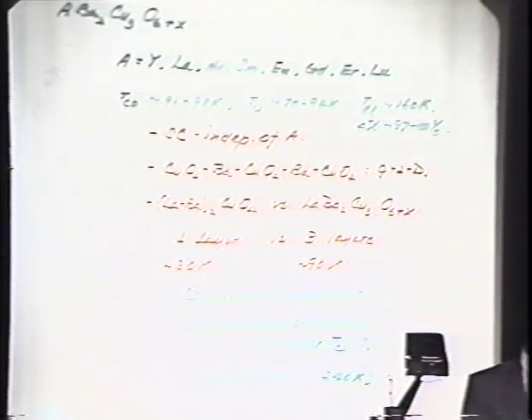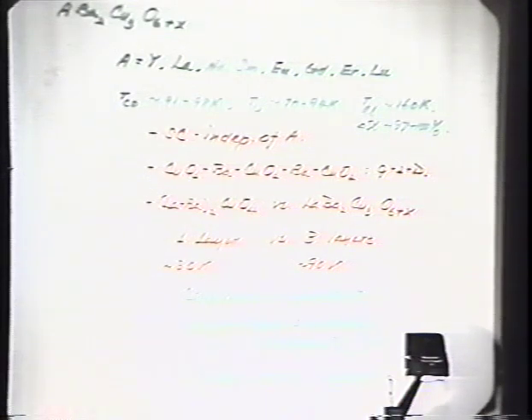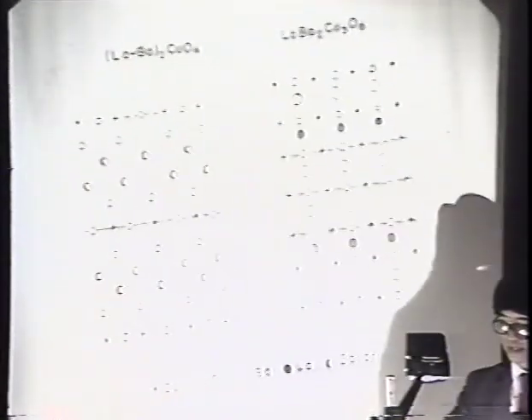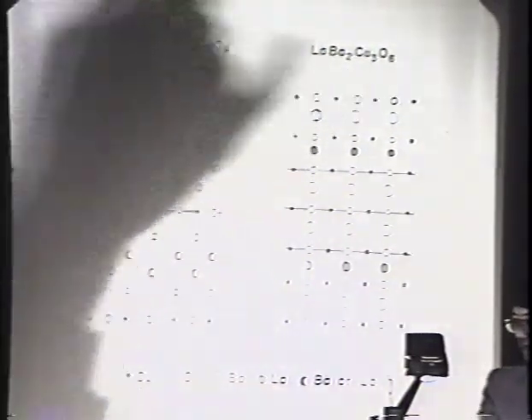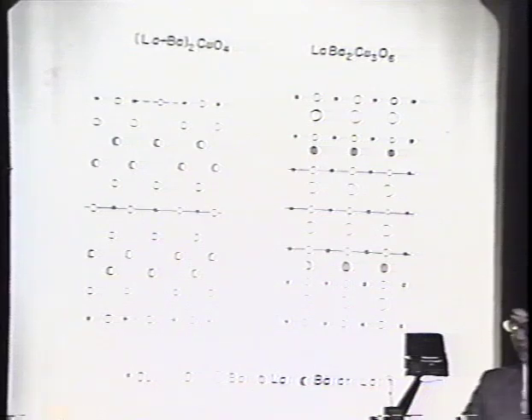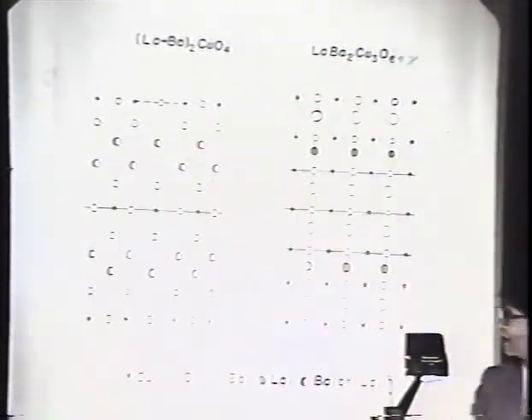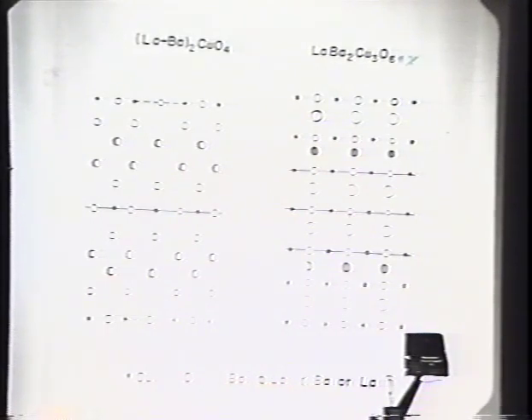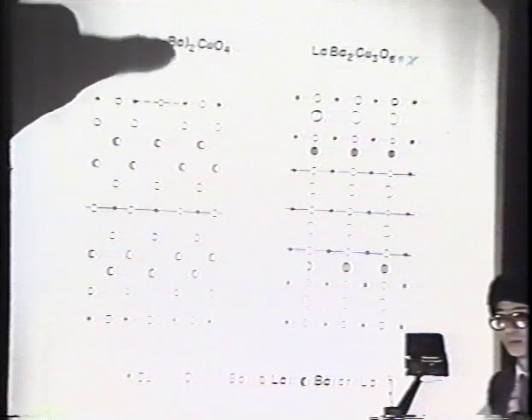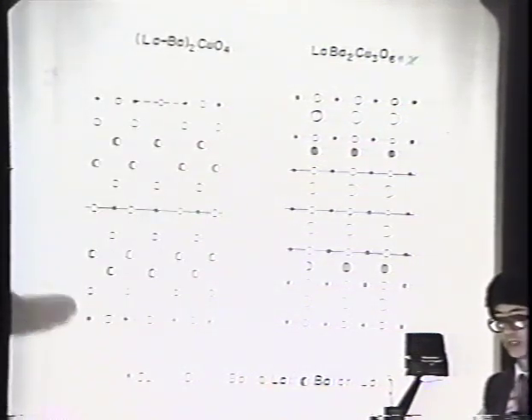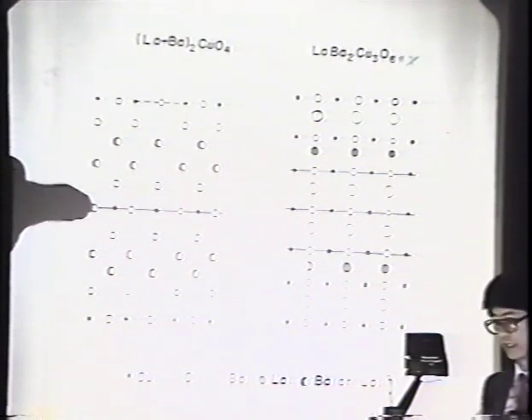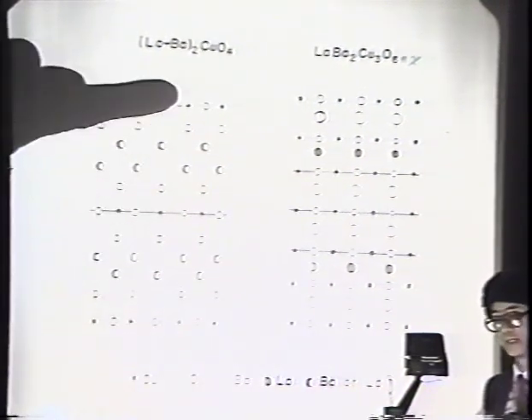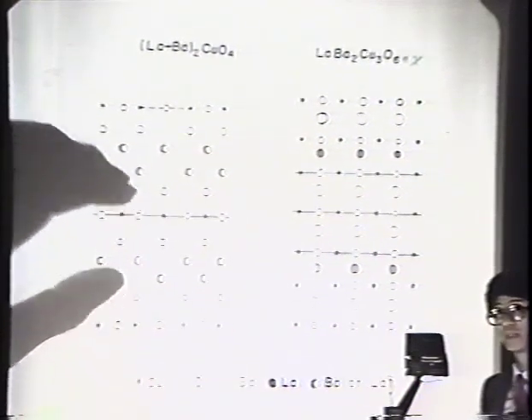And then when we look at the structure, they are quite interesting because they have the layer structure. Actually, it has CuO2, this kind of structure. I would like to show this because it is very interesting. Here, I did not put down the 6 plus x; the x I haven't put in. Basically, if we look at only 6 without the x, that's the structure. And the most interesting part is this: when we look into lanthanum barium copper oxide, La2-xBaxCuO4, the layer structure, this is the structure. You have layers of copper and oxygen, CuO2 layers going like this, here and here, and they're separated here. According to band structure calculation of Lenny Mattheiss and also R.